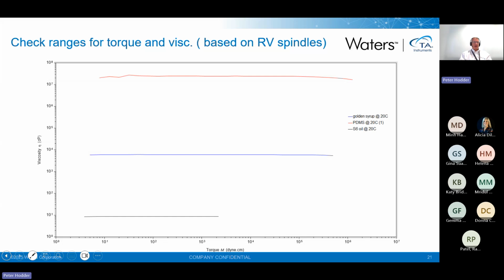The black line at the bottom, the lowest viscosity, has a viscosity higher than water, but it is a very low viscosity Newtonian oil. The blue one represents golden syrup, something you're familiar with from the kitchen, and again, it's a Newtonian material. And the top one, the red one, is actually a room temperature polymer melt. It's a low molecular weight, so it is a liquid. It's still pourable. However, we're not going to get too involved in polymer melts in this example.